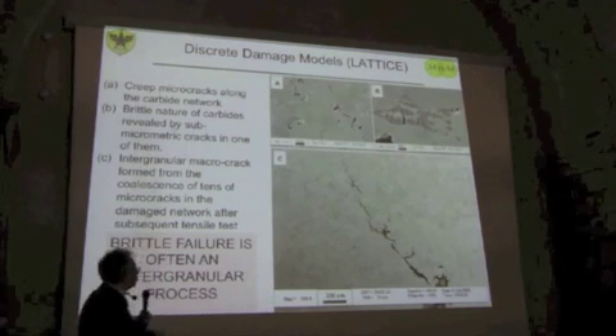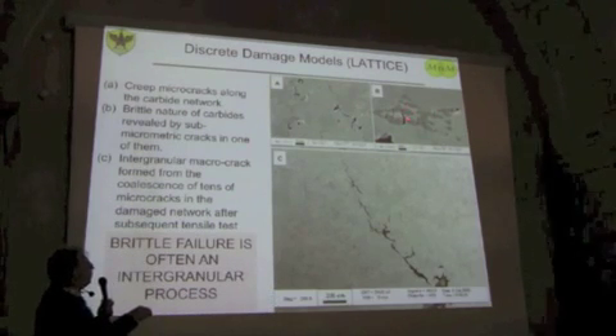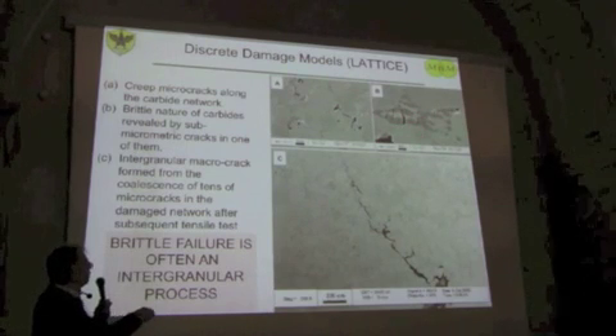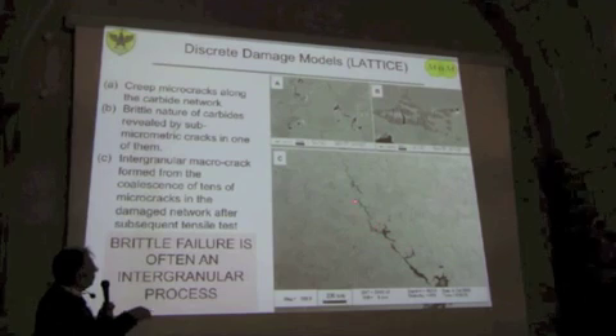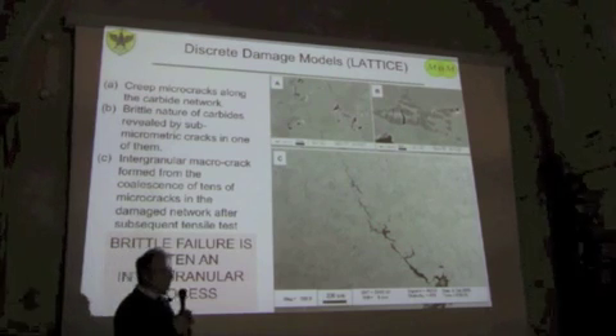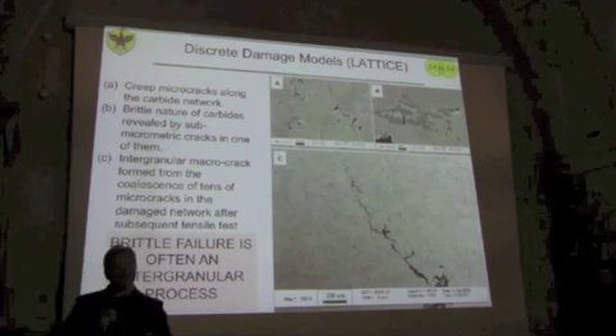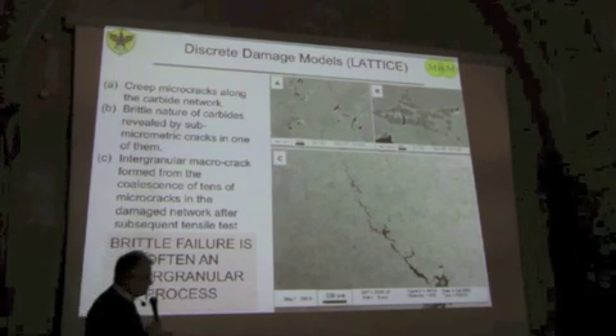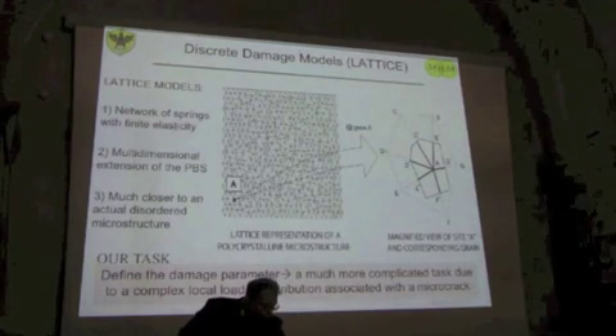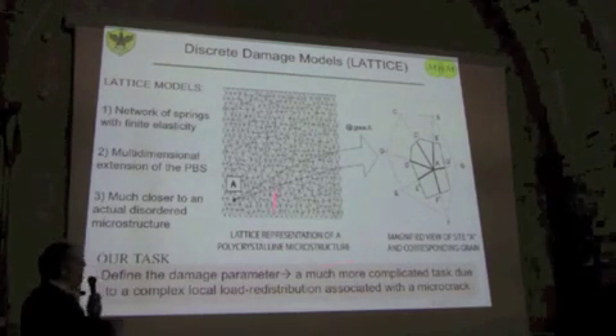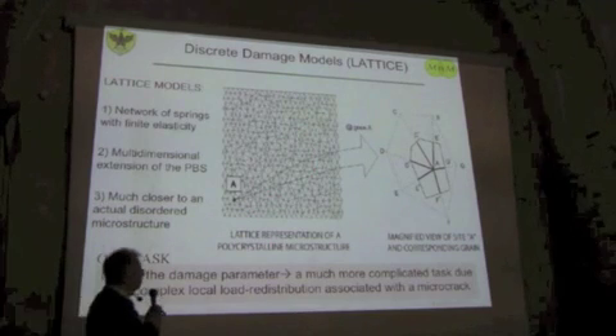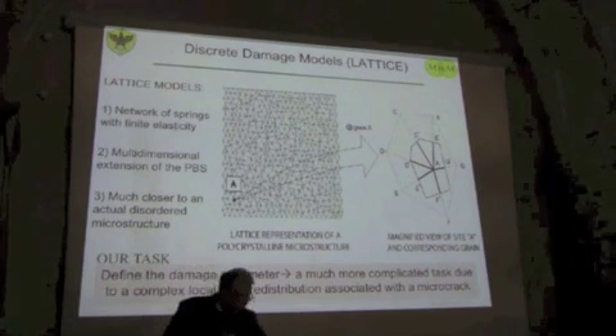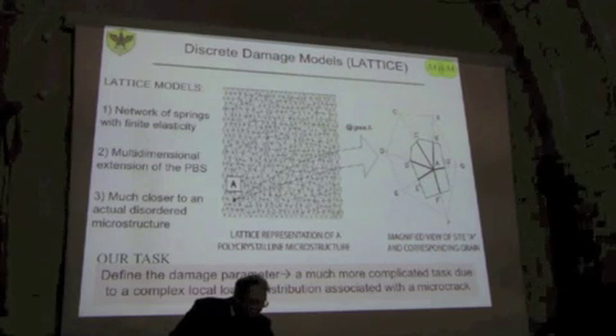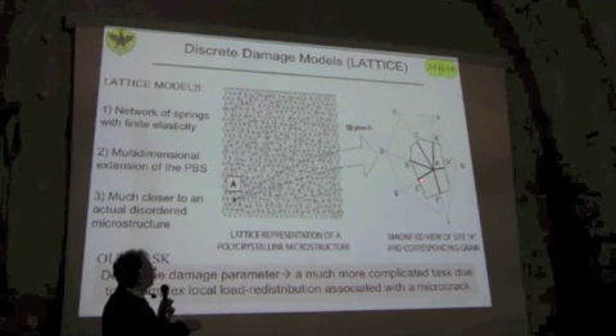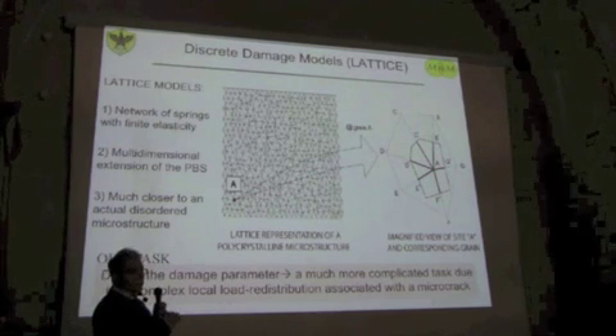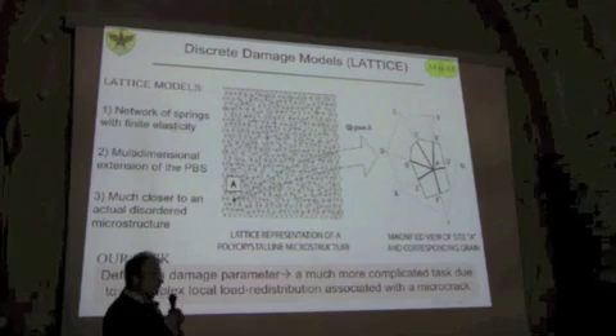These are just pictorial things that I'm throwing at you. You can see nanoscale cracks on brittle phases in multi-phase materials, and you can see cracks propagating through a polycrystalline material that has been embrittled by exposure and by creep deformation for 10 years at 900 degrees Celsius. So, let's say that from those material systems we can come up with a simplified representation that is a lattice based on typical Delaunay simplification. So each grain gets associated, maps into a node in the lattice, and all grain boundaries map into links.